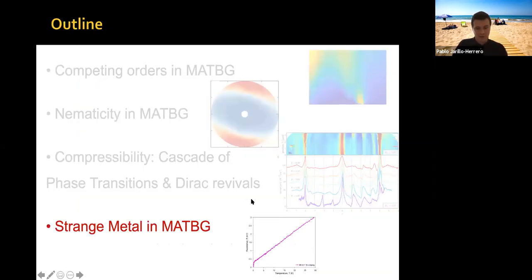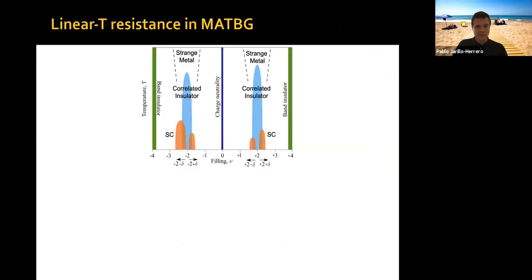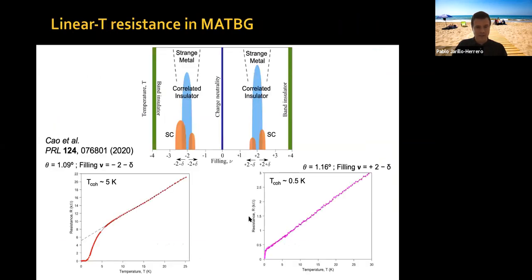I'm going to skip the strange metal behavior. This is maybe just a slide to stop. Again, this is published so you can look at it. If you measure the resistivity versus temperature near this correlated insulator region, in particular above a small superconducting dome, you see this beautiful, perfectly linear behavior. If you have high Tc, of course, the linear resistivity behavior deviates once you reach superconductivity.